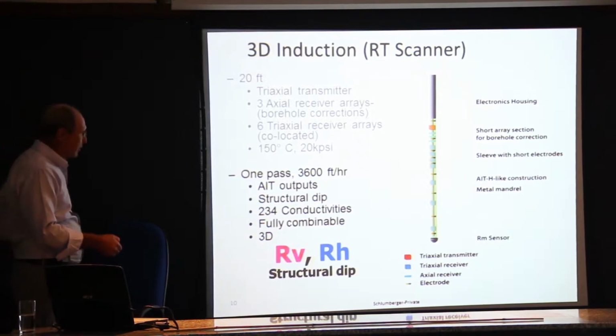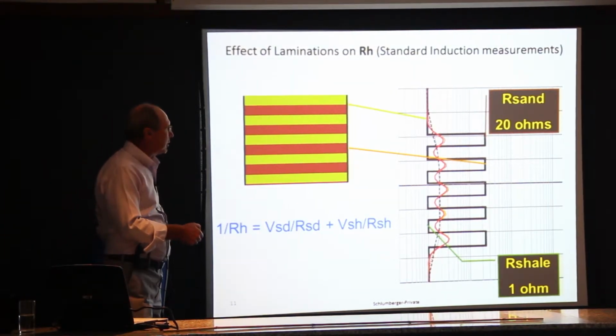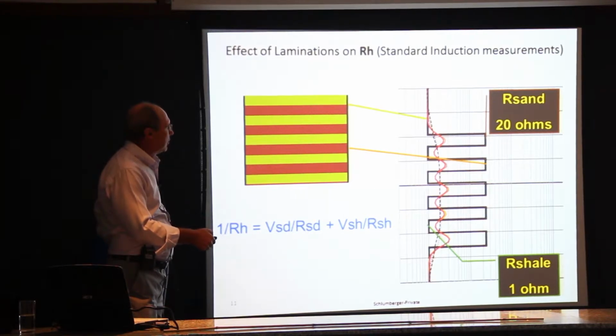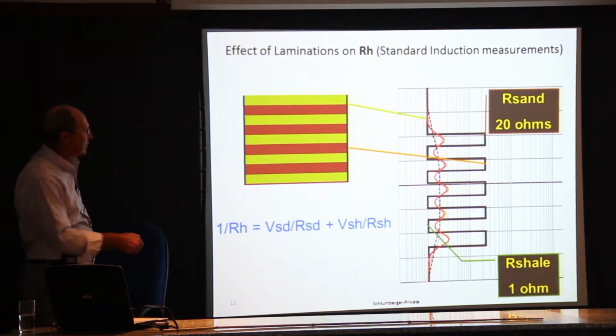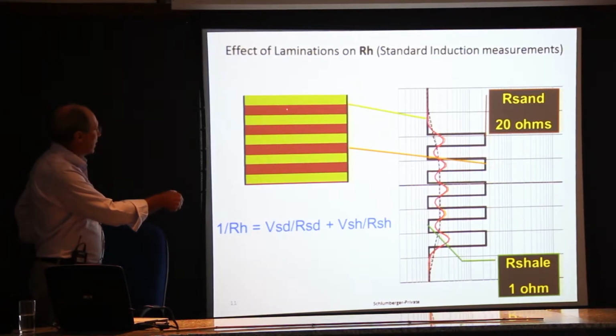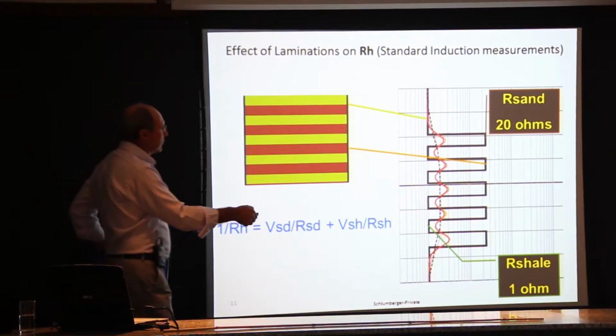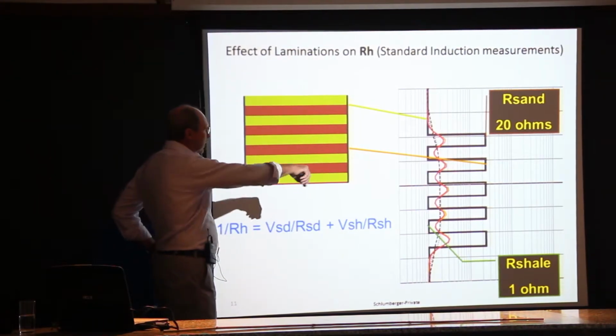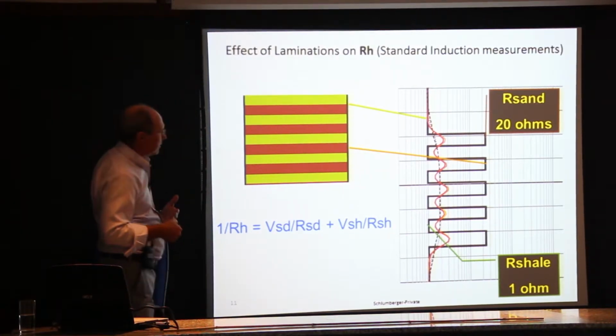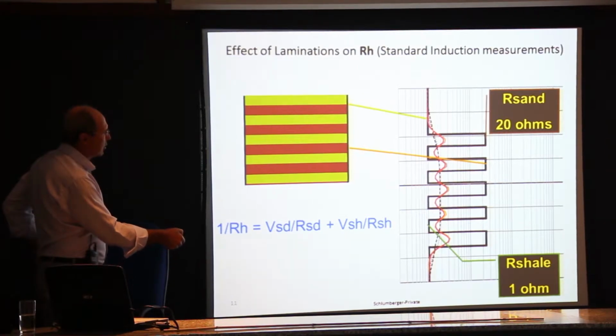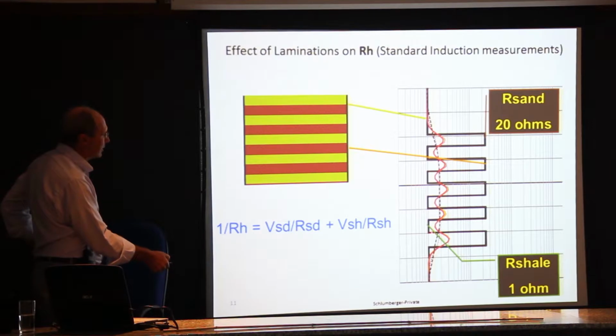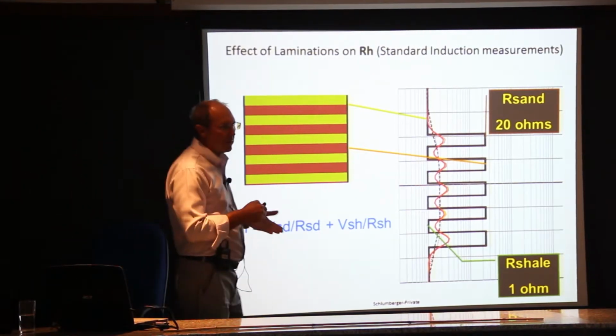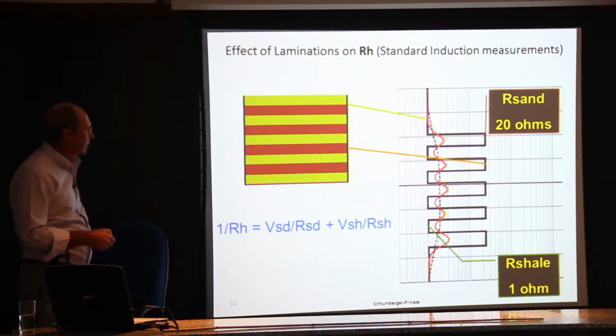Now, we occasionally use this in the pre-salt, because in the pre-salt you can sometimes have what we call laminated formations. And here's an example of a laminated formation where you have a shale with thin layers of sand in between. And if you went with the older style induction log, where you had this shale sand, and if the sand had hydrocarbons in it, the hydrocarbons would make the resistivity read high. But because the current is flowing in this direction, you're essentially just measuring the shale resistivity. The overall effect is a resistivity curve like this. And we're not really measuring the true horizontal resistivity in these thin sand layers that are filled with oil when we have a single induction log like this.